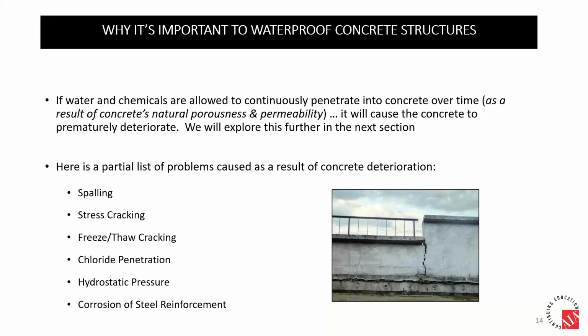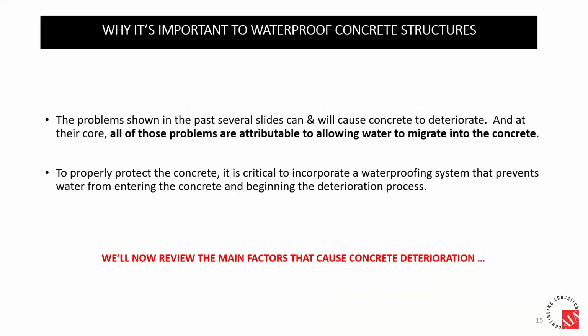So if water and chemicals are continually allowed to penetrate the concrete, it will cause premature deterioration of the concrete. Some of those types of problems are spalling, stress cracks, freeze-thaw cracking, where the surface of the concrete has water and then freezes, chloride and salt penetration, hydrostatic pressure, and then corrosion of the steel reinforcement. Most all of this is caused because of allowing water to penetrate into the concrete. So it's critical to protect the concrete the right way.